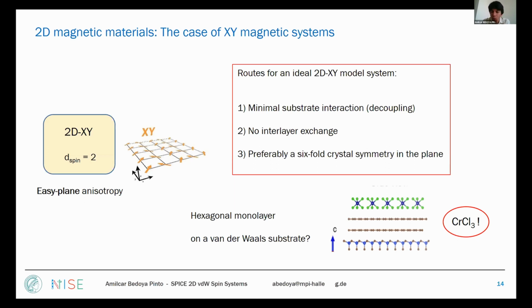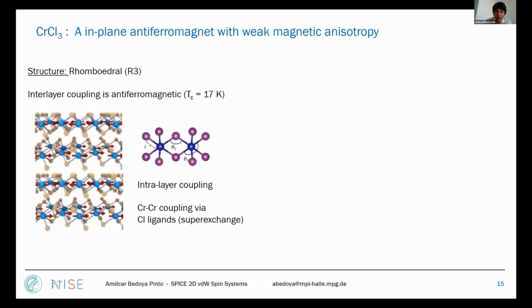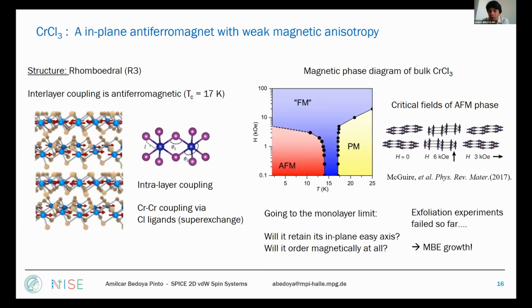And in that case, we went for chromium chloride. This is an in-plane layered antiferromagnet in the bulk. I think there have already been talks about these materials before, so I'll be very short in explaining, just picking up the relevant points. It is a layered antiferromagnet with spins pointed in the plane, and the intralayer coupling, so within a layer, is mediated by superexchange via the chlorine ligands. The bulk TC is 17 Kelvin. It was, of course, also well studied in the bulk.